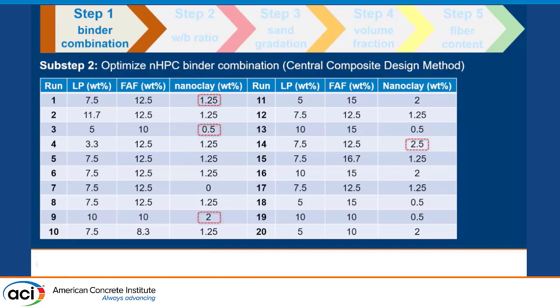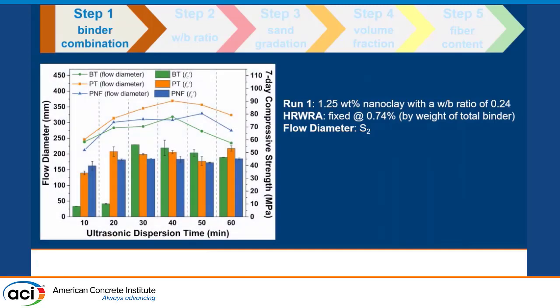As you all know, the dispersion of nano-clay in the cement paste can significantly affect the compressive strength. So we need to first determine the best dispersion time for the ultrasonic dispersion of the nano-clay. So we use the run with 1.25% nano-clay content, a preliminary water-to-binder ratio of 0.24, and a fixed amount of high-range water reducer in the mixture to test the flow diameter of the fresh mixture, so that the optimum dispersion time of the nano-clay can be determined.